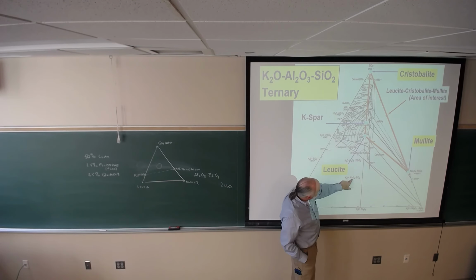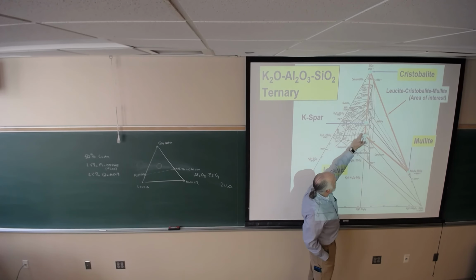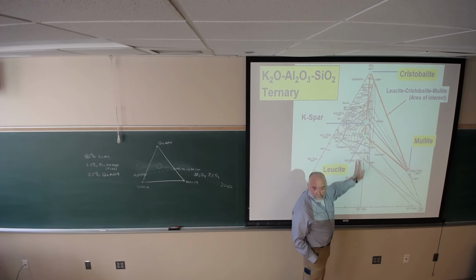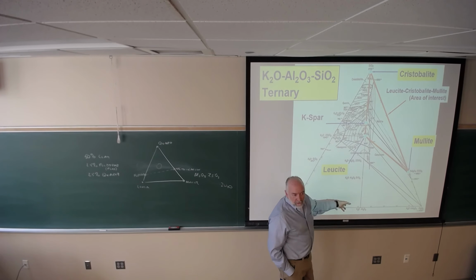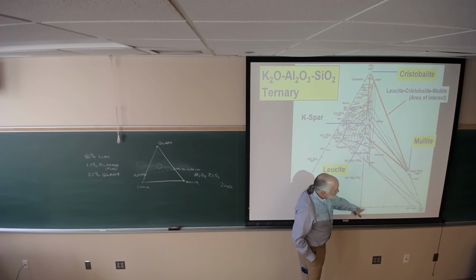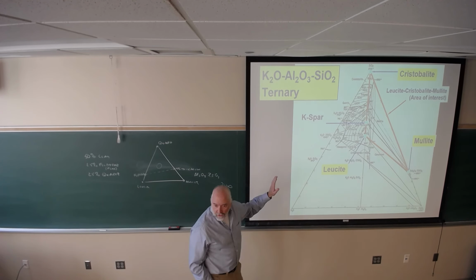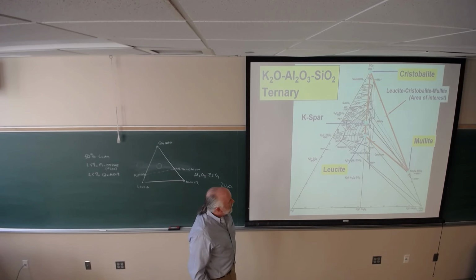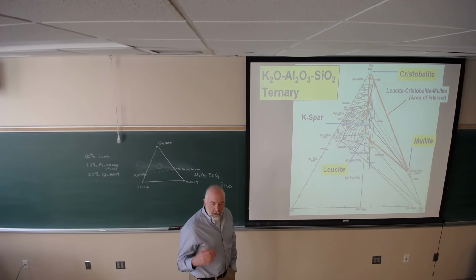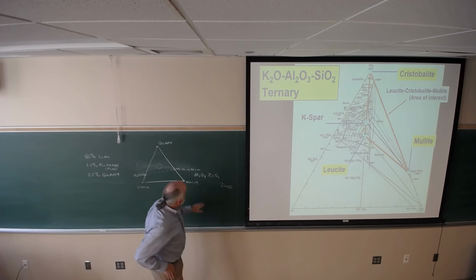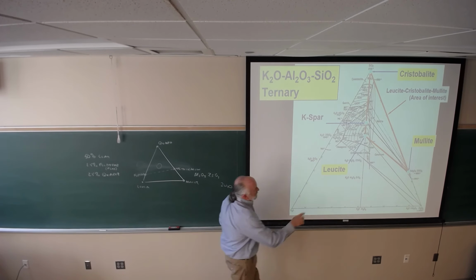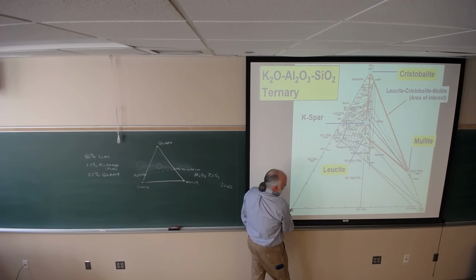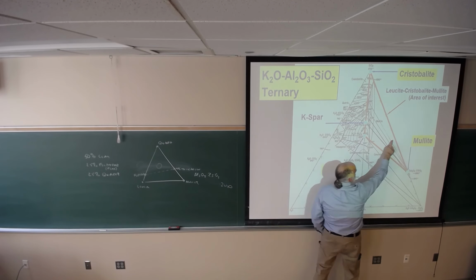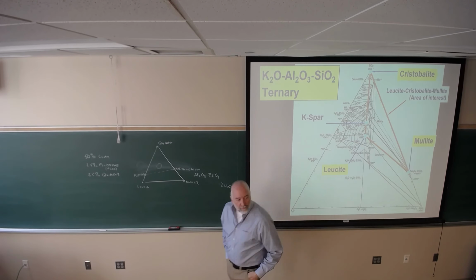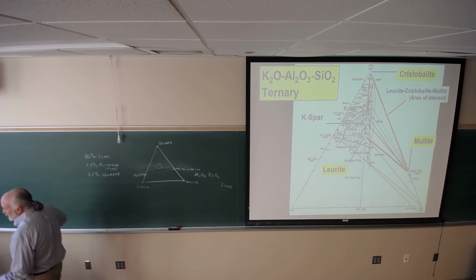So you have 1 potassium, 1 alumina, 1 silica; 1 potassium, 1 alumina, 2 silica; 1 potassium, 1 alumina, 4 silica; 1 to 1 to 6 for feldspar, so they all fall in that line. That's pretty slick, right? And here's 1 potassium, 1 alumina. Those are all stable compounds within this phase diagram. If I want to know where clay sits, I have this 1 alumina, 2 silica. Here's 1 alumina, 2 silica. I can draw a line from potassium through that point to here, and that would be where metakaolin would sit. Don't worry, we're going to play with this some more.